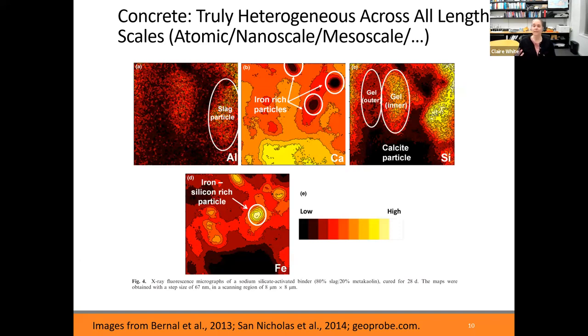The results that we get from the atomistic level can be used to infer what's happening at the macroscopic level, or say how you change the chemical composition, how that might affect the macroscopic level. But there are other properties at different length scales, such as the micron length scale, that are also important to know. This is X-ray fluorescence data of alkali-activated slag. You can see here we've circled an unreacted slag particle. There's also these iron-rich particles. The gel's forming, but the gel isn't uniform. There's different compositions, and this is only 8 microns in size. So there's a lot of heterogeneities even at the micron length scale.